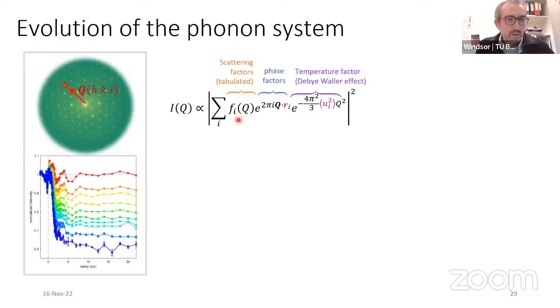One of them is one I will not touch. It's just how strong every ion scatters. Typically heavier ions scatter more, lighter ions scatter less. This is true for electrons and it's true for X-rays. It's not true for neutron scattering. This is a phase factor where the positions of the ions come in, their positions within the unit cell. And here we have the temperature factor, the Debye-Waller effect, meaning that if an atom moves more around its high symmetry position, it reduces the overall intensity.